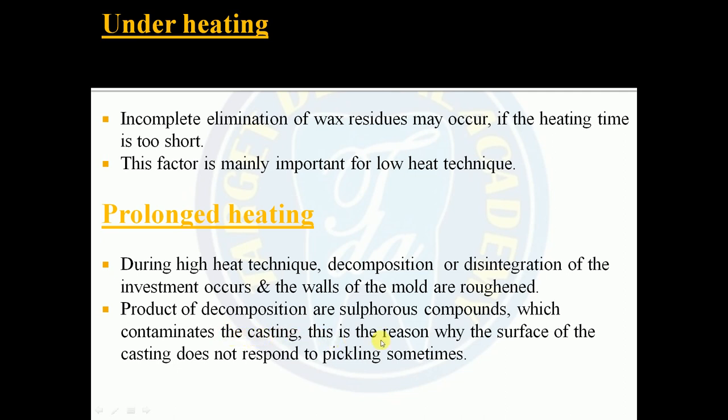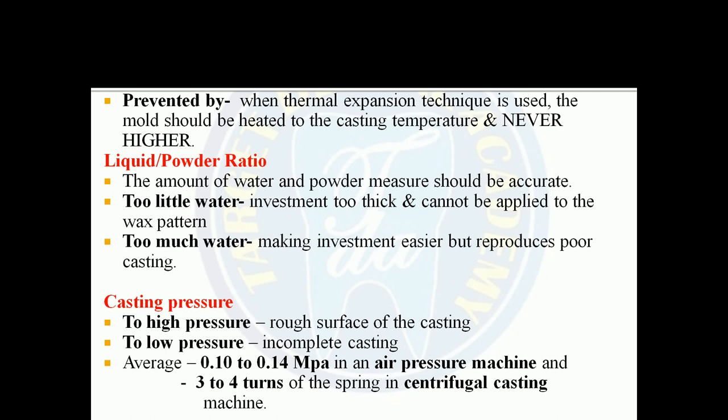So this is the basic reason why the surface of the casting sometimes does not respond to pickling. Why? Because the products of decomposition are sulfurous compounds which contaminate the casting. Very important point. It can be prevented when a thermal expansion technique is used. The mold should be heated to the casting temperature and never higher than the casting temperature.